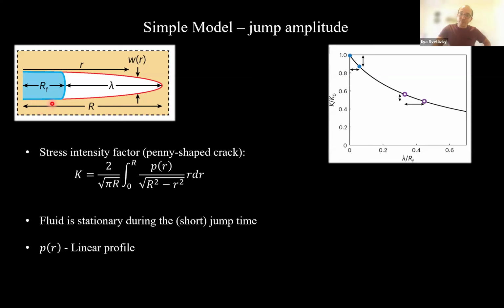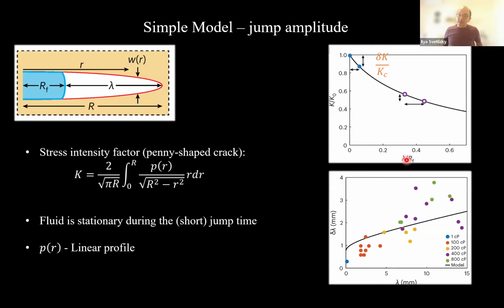The key point is that if we plot the stress intensity factor versus the lag, we see this functional form, decreasing value. So the larger lambda, the smaller K, very similar to the point forces that I described. But importantly, if we assume the same observation that Ravishankar saw, that delta K, the difference between the nucleation toughness and the arrest toughness, is roughly 10%, this figure suggests that if your lag is larger, for the same 10%, you would get a larger jump of your crack, right? So this is the x-axis. And if you plug the numbers, the framework explains reasonably well the amplitude of the jump versus the lag.